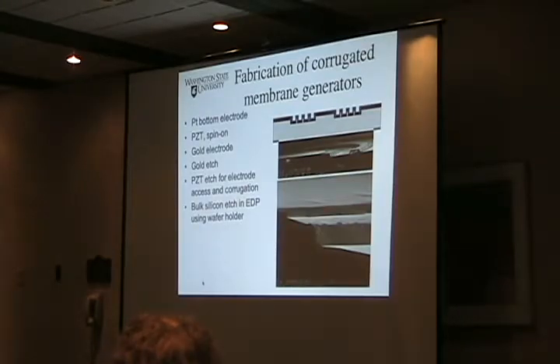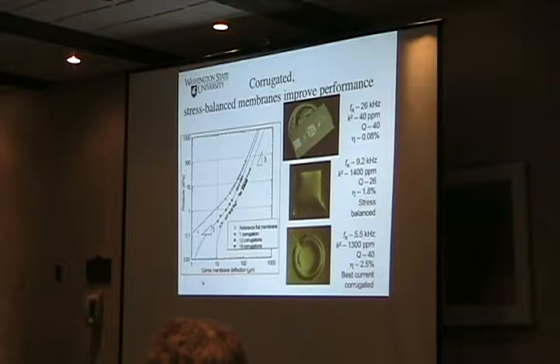The one other way to relieve some stress would be to go ahead and corrugate the structure, so that we had a piezoelectric membrane here and had some corrugations that could relieve the stress during thermal processing, and just pattern it, wet etch it, because I'm, again, inexpensive. My wife says I'm cheap, but I'm inexpensive, and we end up with a corrugated structure. And so we can now have a corrugated piezoelectric structure, a low stress structure, or the original high stress structure.